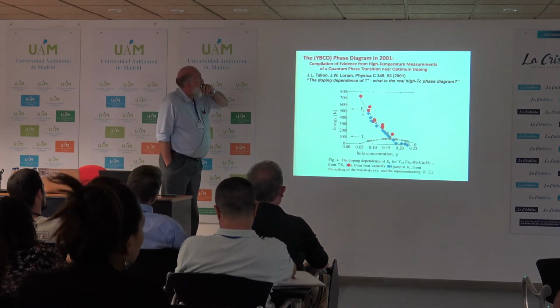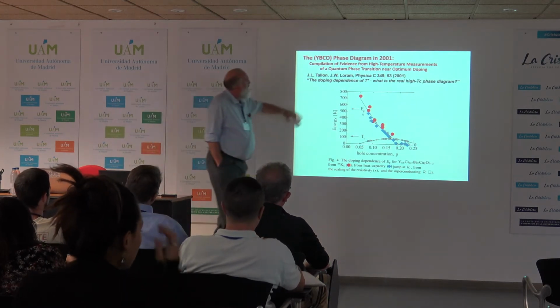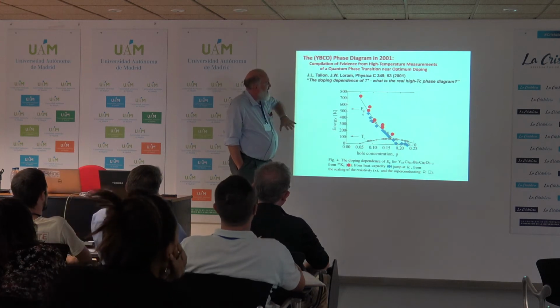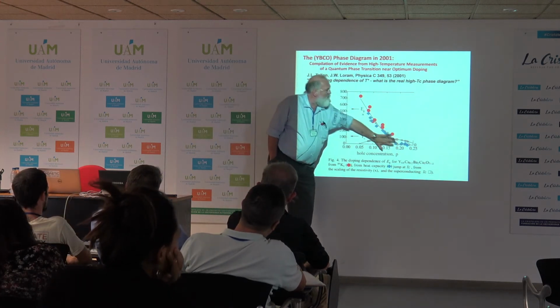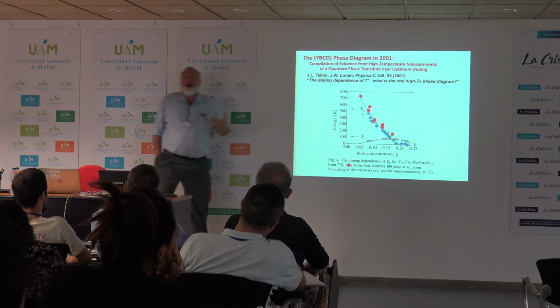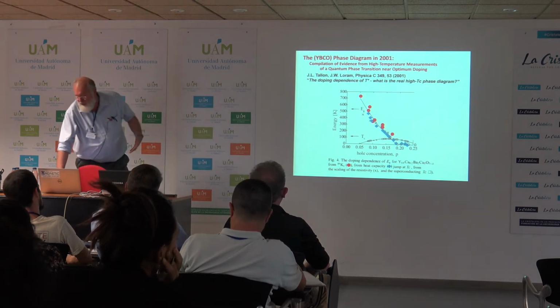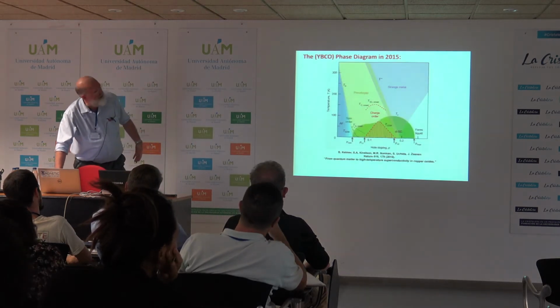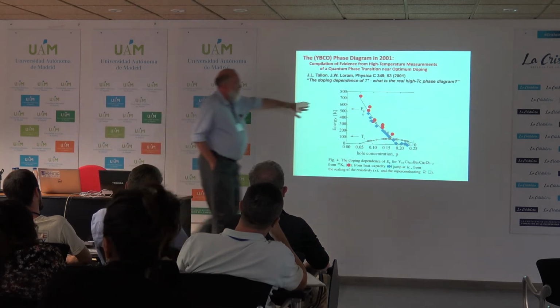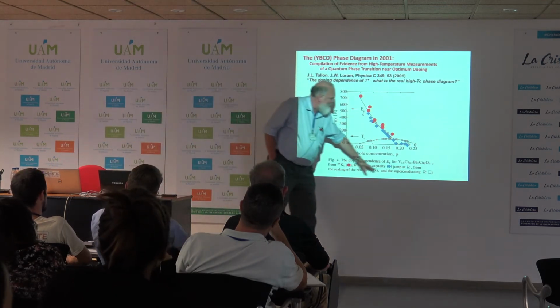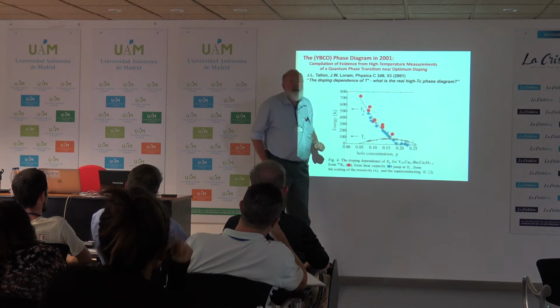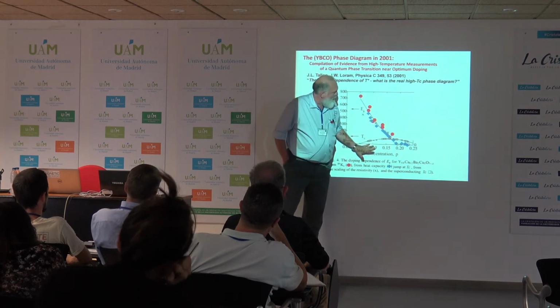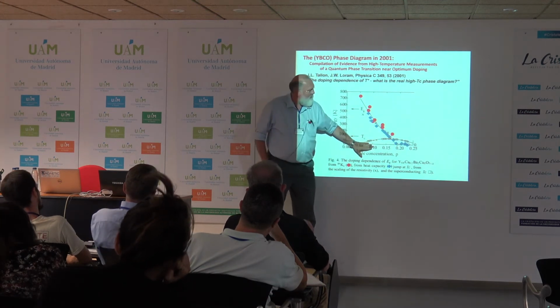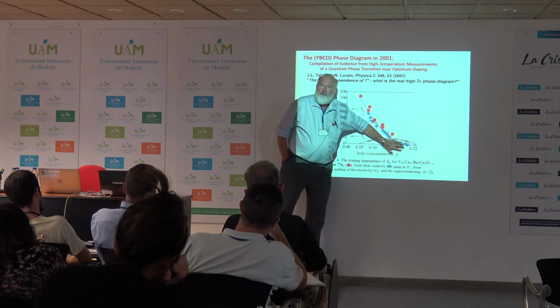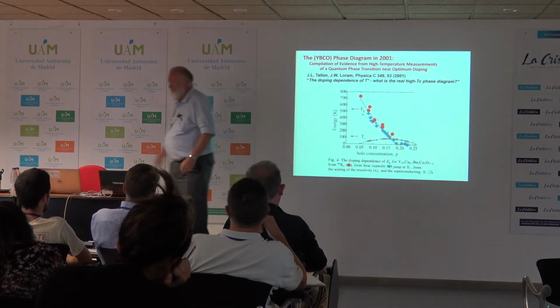This was already shown by Tony, so I'll just point out that the YBCO phase diagram in 2001, all of these measurements were taken at high temperatures. So even the data points that are down low on this plot were taken from, for example, heat capacity up at TC. And so our philosophy will be to then suppress the superconducting dome to actually measure physical properties in this low temperature limit.